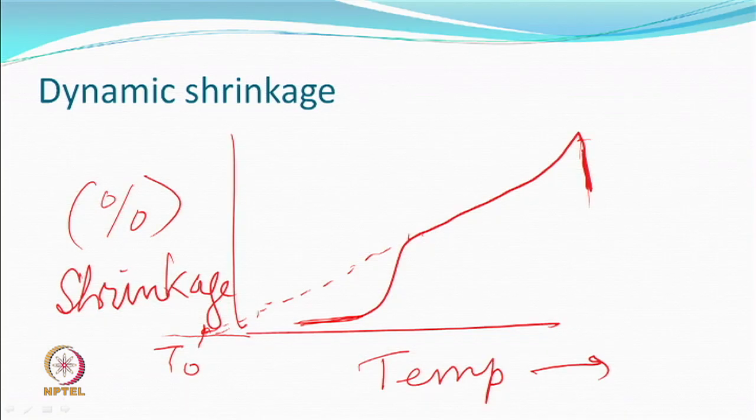So, if T0 is higher or T0 is lower, if T0 is a minus value, then you are quite sure at room temperature also you can do texturing. If the T0 is coming to, let us say, 40 degrees, so definitely you can't do anything below 40 degrees, you have to go above 40 degrees to do certain things. Therefore, we say that it is a combination of time and temperature and a solvent and polymer together. So, this particular curve is a very useful curve, think of it.